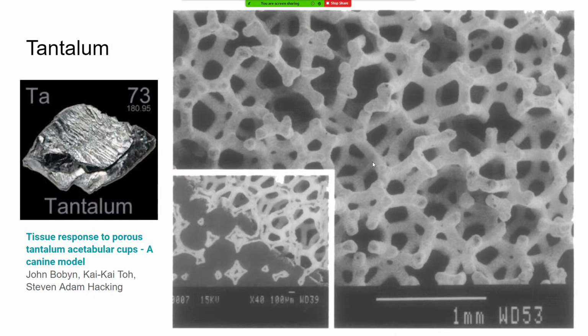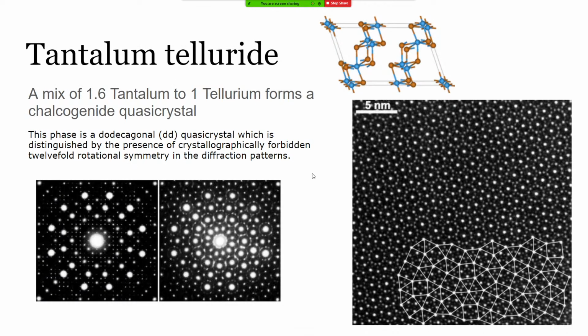Tantalum has an interesting structure as well, and again, it has a really good response to the human body for implants and stuff. A mix of 1.6 tantalum to 1 tellurium forms a chalcogenide quasi-crystal, which is a dodecagonal quasi-crystal phase, distinguished by the presence of crystallographically forbidden 12-fold rotational symmetry in the diffraction pattern.